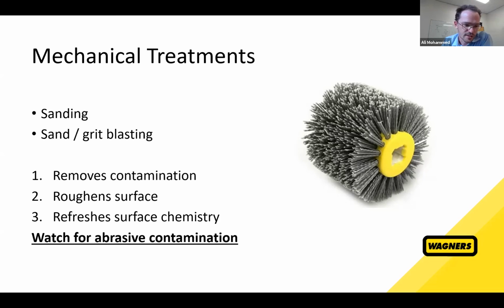One thing I will note is that if you're using an abrasive type process, just watch for contamination. The abrasive itself might be contaminating the surface, or, for example, this brush on the right, a nylon type brush, if that's smearing on the surface and getting hot, it can leave a contaminant on the surface. So you always have to be very careful with these sort of physical contact type applications, that you're not worsening it by leaving something behind on the surface.